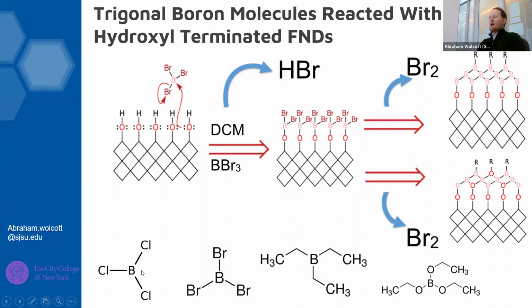In the bottom of the slide, you'll notice that all of these precursors are trigonal. This is highly reactive and is an electrophile, and we found that all of these do a similar level of chemistry. Now, the reactivity increases with the halides, but these other types of ligands on the surface, whether it's an ethyl or an ethoxy group, are also reactive to the diamond surface. And that's because these are planar and the boron center is highly electrophilic.